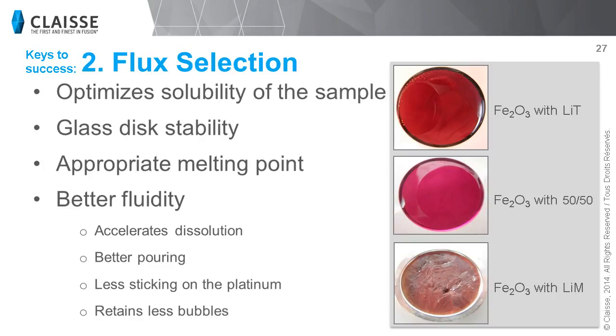You can see we have obtained a disc with bubbles and vectors showing different oxidation states of the sample. In the middle, we have used a mixture of 50% lithium tetraborate and 50% lithium metaborate. We have obtained a clean disc without any imperfection. Finally, on the bottom, the iron sample was fused with pure lithium metaborate. You can clearly see the disc is impossible to analyze since it has crystallized. Keep in mind that the proper flux will give you the best result for this dissolution.